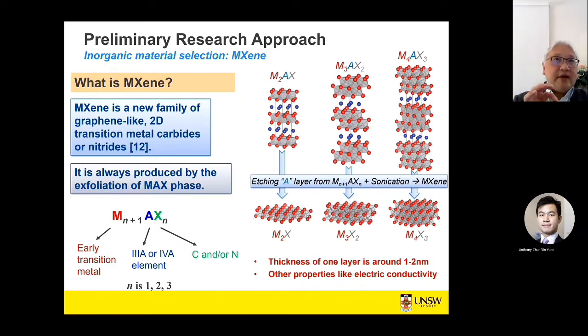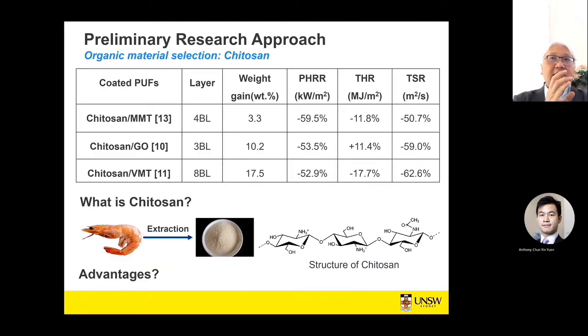And what we have found is that MXene has a very superior fire retardant performance, and also it has other functionalities like good thermal and electrical conductance as well. So it's really a multifunctional material. And as we explore what other organic compounds can be complementary to MXene, we have found that we can use chitosan, which is basically an extract from prawn shell, and also other nano compounds, for example VMT, which is vermiculite, or MMT, which is montmorillonite as well.